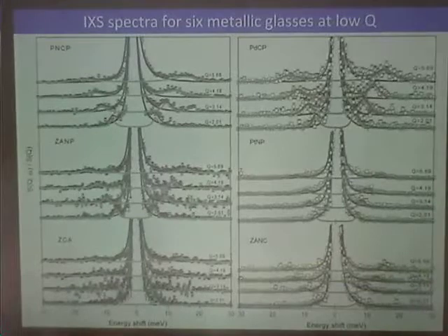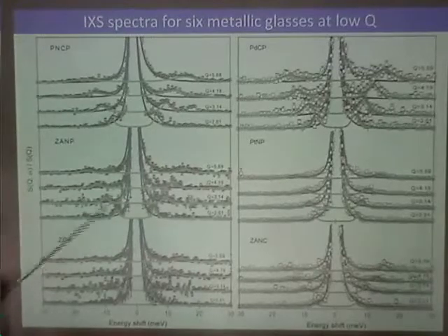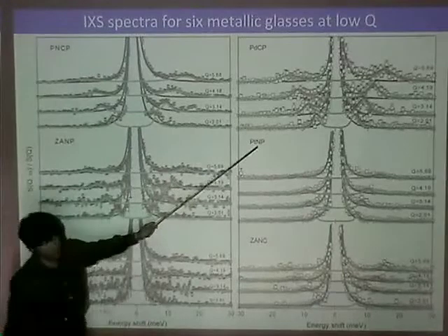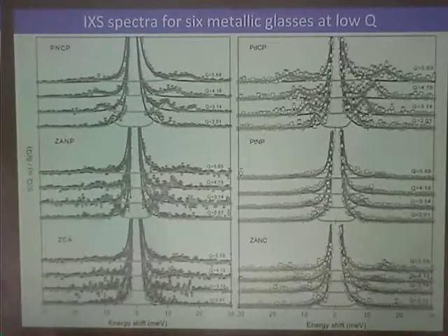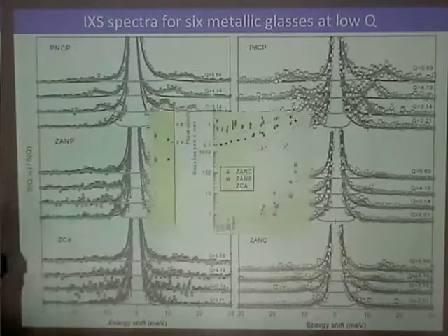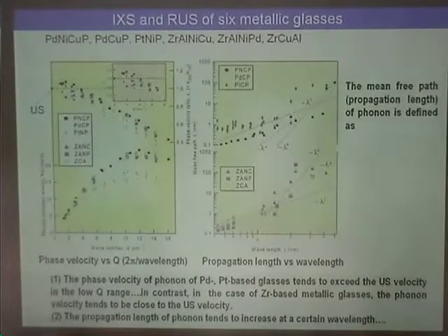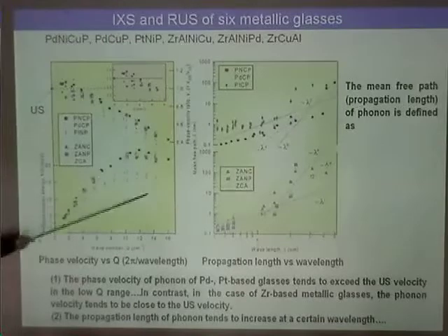So we have performed measurements for 6 types of metallic glasses. Other than the palladium nickel copper phosphorus, they are zirconium aluminium nickel phosphorus, zirconium copper aluminum, palladium copper phosphorus, platinum nickel phosphorus, and zirconium aluminium nickel copper metallic glasses. This is the dispersion relation for the 6 metallic glasses.